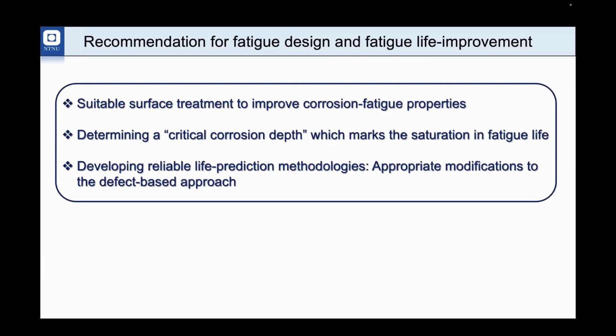So these are my recommendations for fatigue life improvement. We should look for a suitable surface treatment method. For example, glass bead blasting can impart some work hardening or compressive residual stress, but we have not got enough evidence that it can also change the microstructure significantly. So probably some treatments like laser shock peening could be a better option.